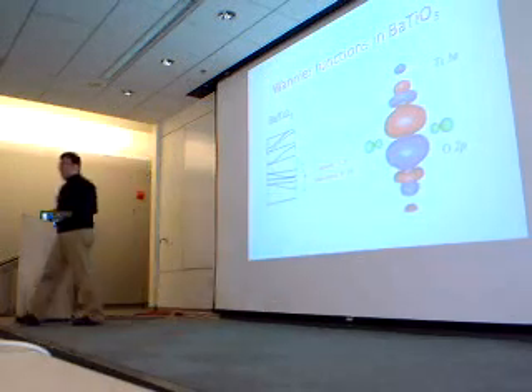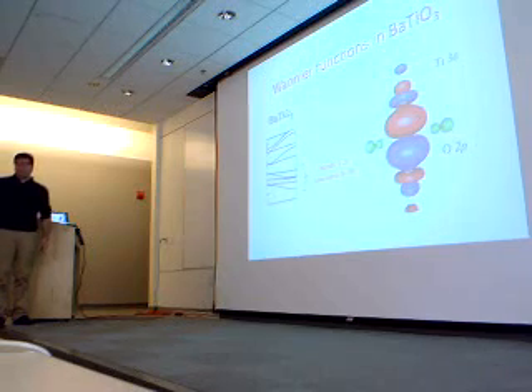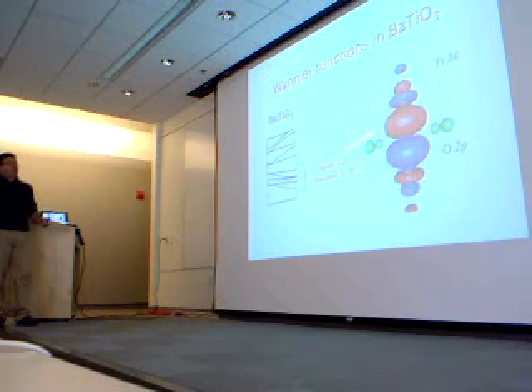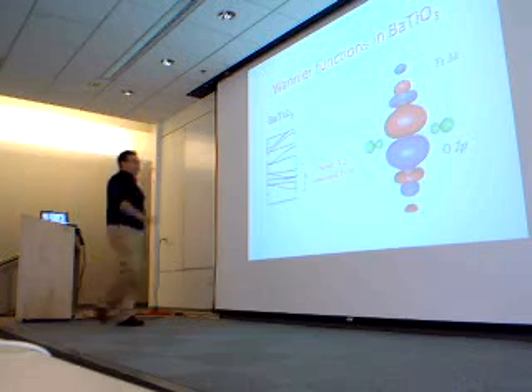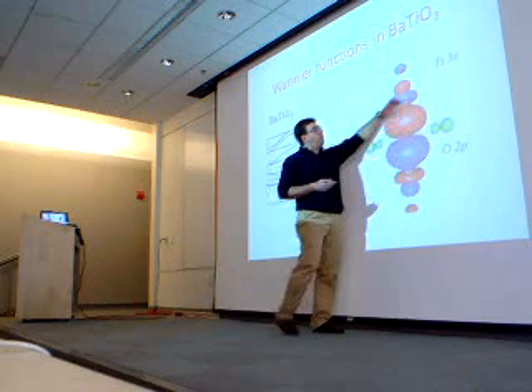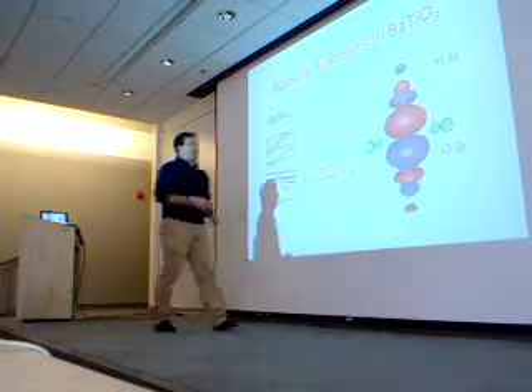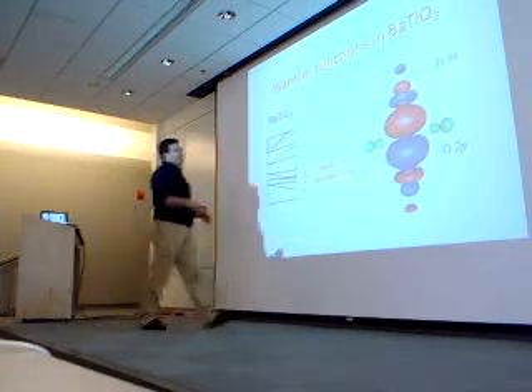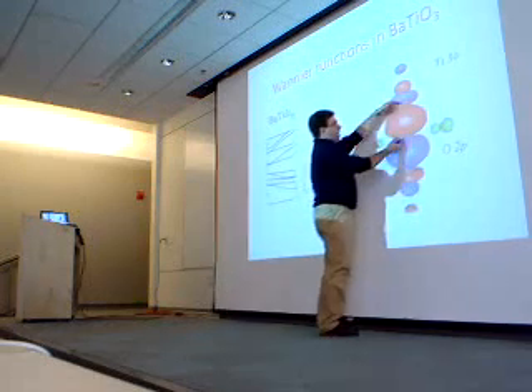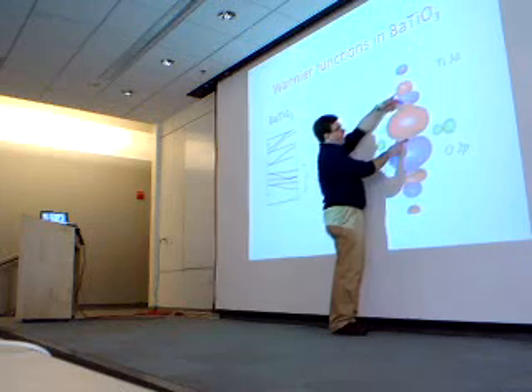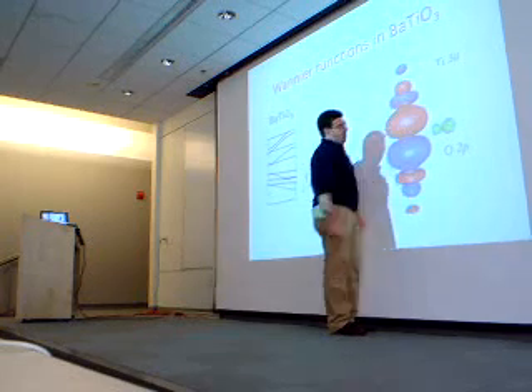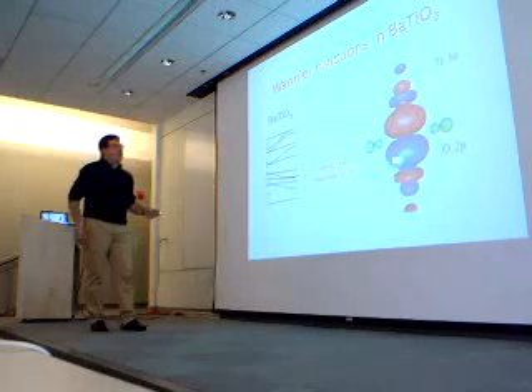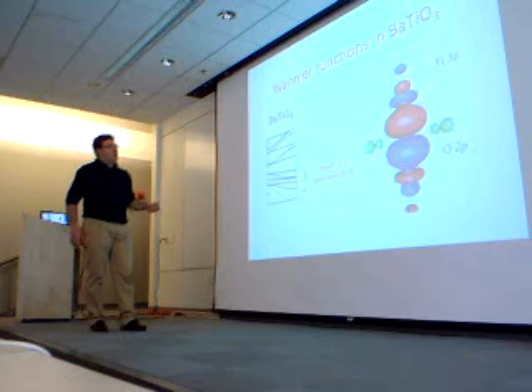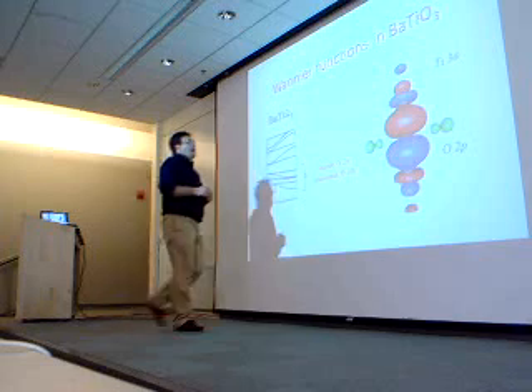So this is an example, say, of the chemical intuition. Everyone thought that ferroelectric perovskites are ionic materials, but in reality, if you look at the electronic structure of the oxygen, you see that the oxygen bands have a very strong titanium component and a very much covalent-like bonding between titanium and oxygens. And this is the sort of chemical intuition, but you can see the dielectric response of the system being driven exactly by this covalency. Because if you look at what happens when, say, the oxygen cage displaces against the titanium, so here the oxygen, here is the titanium, and here is the other titanium, that is what happens when these bonds become shorter and this bond becomes longer. You'll see, if you look at the Wannier function, that there is a huge charge reorganization. So this bond is really at the border between being covalent and being ionic.